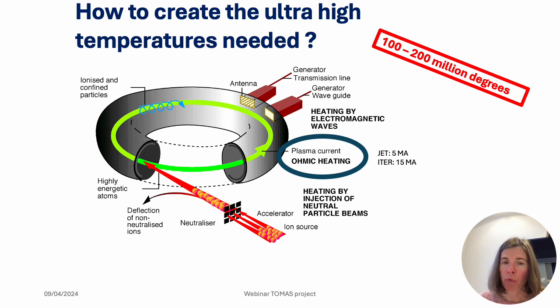The same is true for a copper wire. When you run a current through the copper wire, it will heat due to resistivity. The same happens in the plasma, but it can only happen when there is a current in the plasma. So you immediately notice it is only applicable for the tokamak configuration. In the stellarator, the ohmic heating part is almost non-existent because there is almost no current in the stellarator. In any case, also for the tokamak, ohmic heating alone is not enough to reach our 100 million degrees.